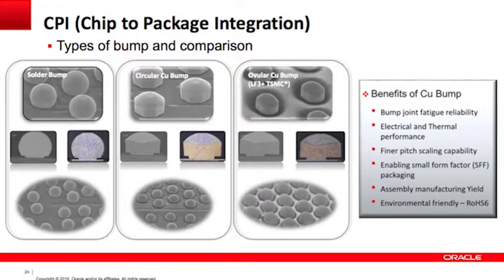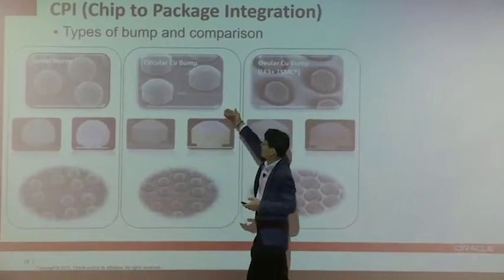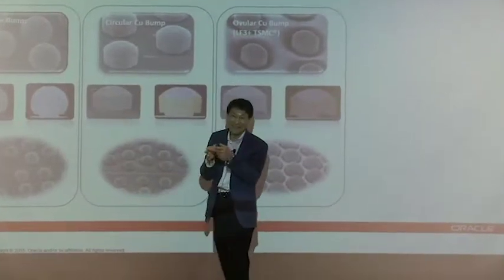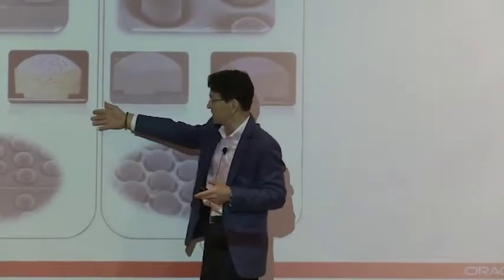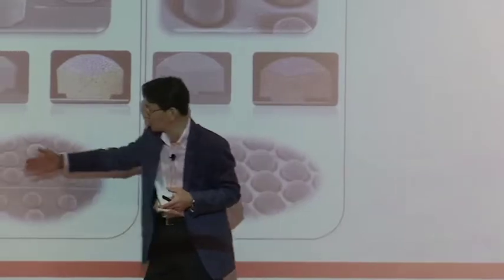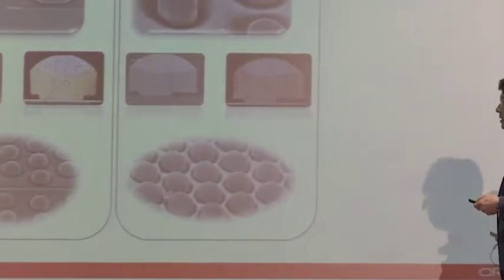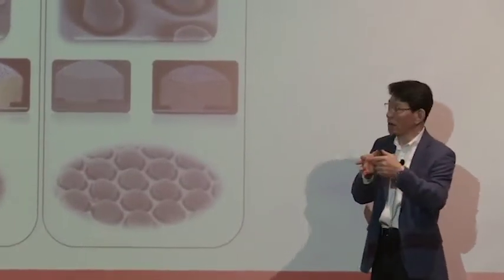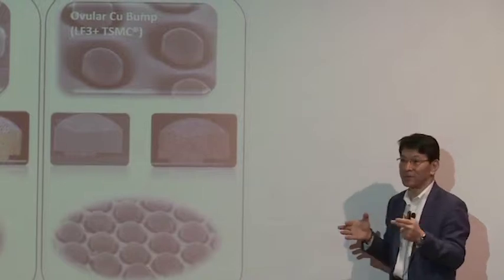So it's a typical example for your eye refreshing. This is a solder bump, an actual image that I took. This is an actual cross section. This changes to a copper bump, from solder to copper. It cannot be a round shape. It is kind of octagonal, but we just say it's a round shape. This is a cross section, and after reflow, it pretty much looks the same. But at the bottom over here, the copper is staying there. And micro bump. Oh, this is an oval shape. From round shape to oval shape could support more mechanical rigidity.